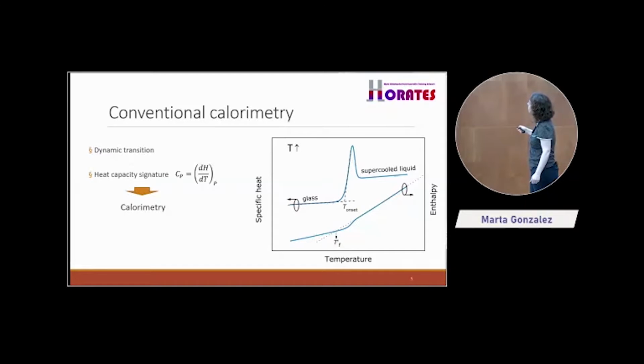This is enthalpy, okay? We started here, and then we go to the extrapolation of the supercooled liquid line, till here, everything is okay. But something happens here, and at this point, this is called the fictive temperature, doesn't matter. At this point, if we are heating again fast enough, the problem is that we are not giving enough time to the system to equilibrate, because if we are heating faster than the relaxation time, we are going to continue being a glass because the system doesn't have time to equilibrate.